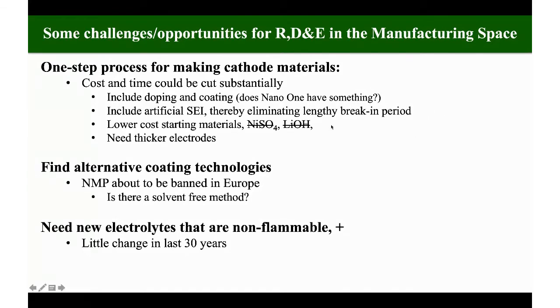And other areas where we need improvement is lower cost starting materials. Most of the NMCs use nickel sulfate. And if you've got high nickel, for example, 80%, you have to use lithium hydroxide. We need to go back to the mine and look at the supply chain from the mine to the customer and see where we can intersect at a lower cost part of it. We also need thicker electrodes so we can get rid of, say, half the current collectors and separators. This will need better ion and electronic conductivity in the raw materials.